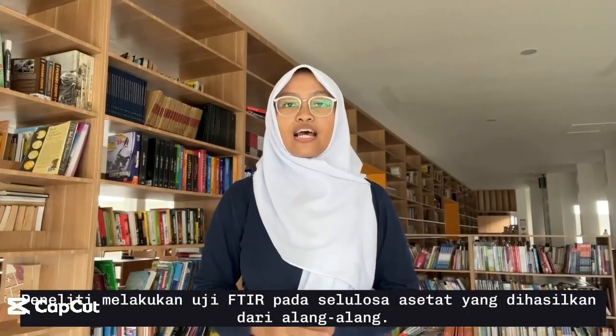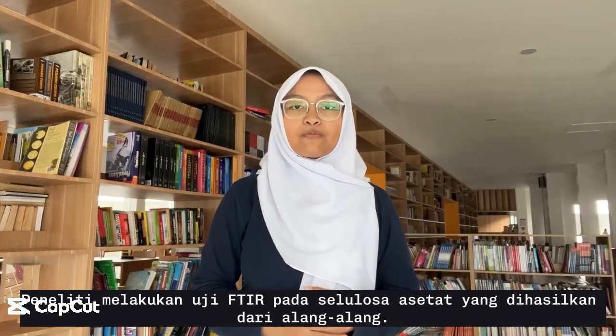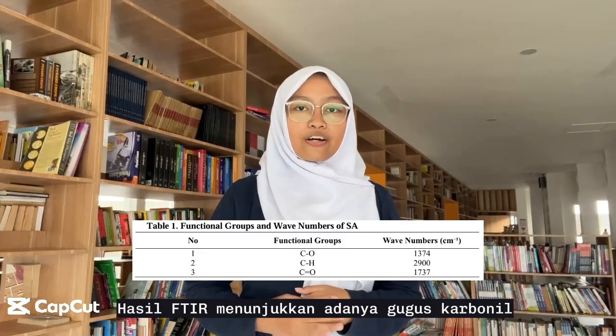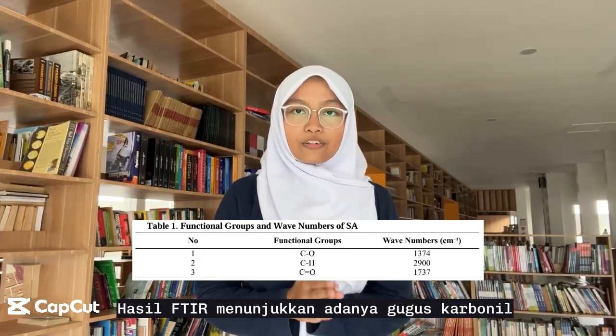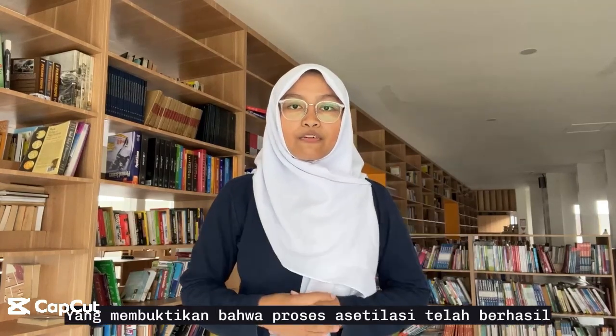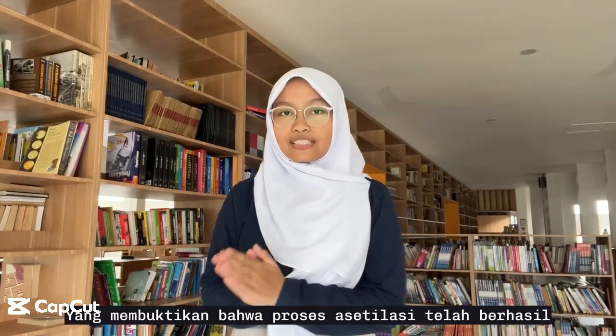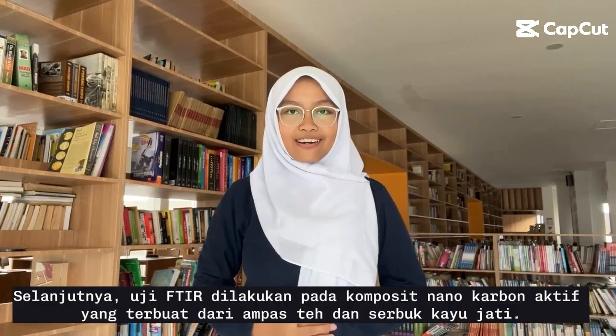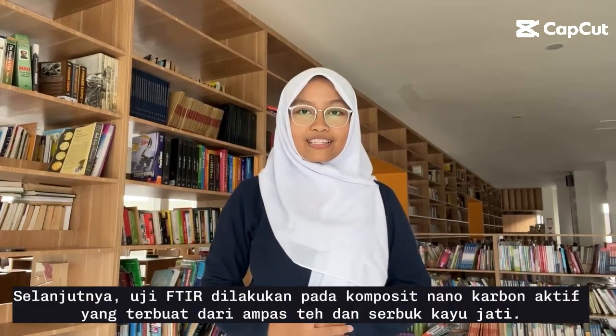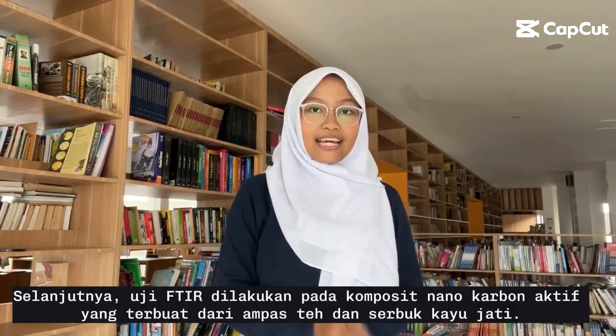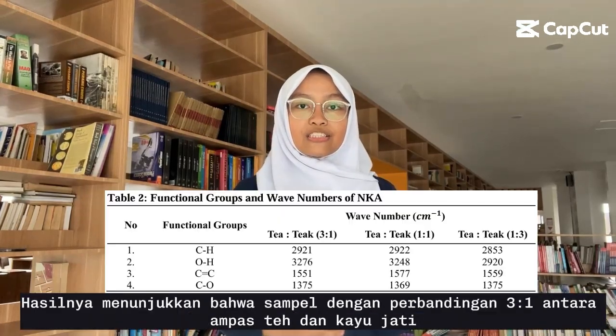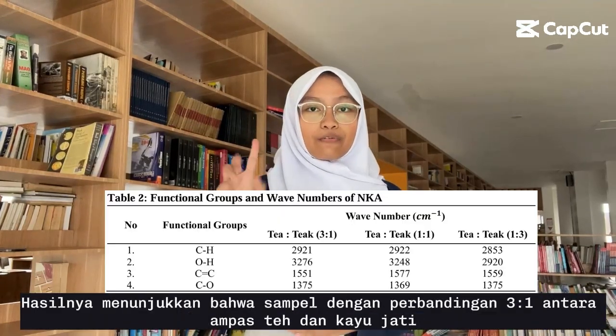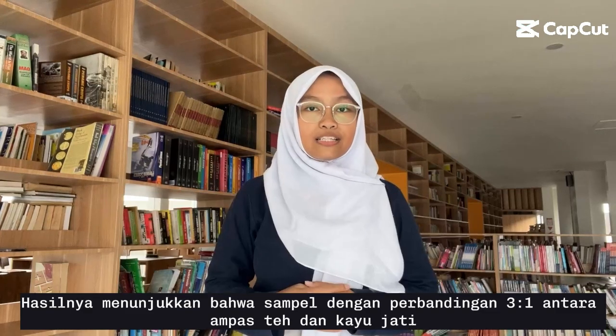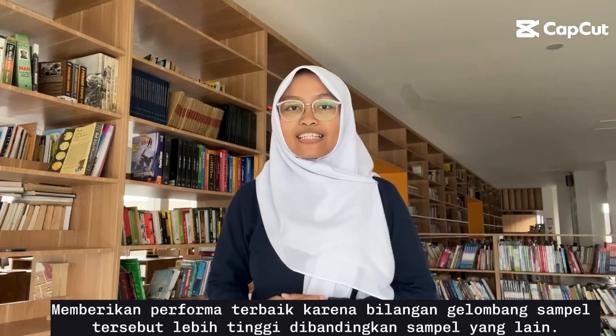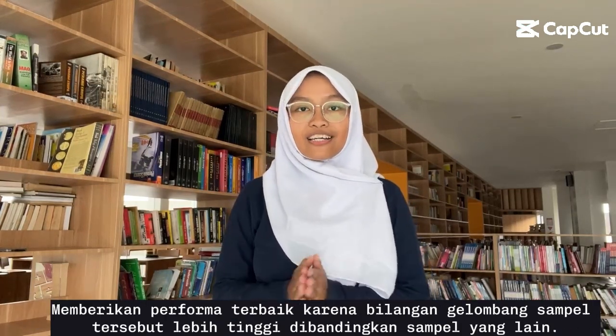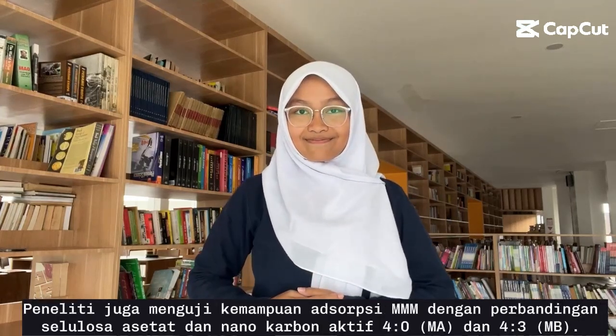The researcher conducted FTIR tests on cellulose acetate produced from alang-alang grass. The FTIR results showed that carbonyl groups exist, which proved that the acetylation process was successful. Next, FTIR tests were conducted on nano-activated carbon composites made from tea waste and teak wood powder. The result showed that the sample of a 3:1 ratio of tea waste and teak wood powder gave the best performance because the wave number of the sample was higher than the other samples.